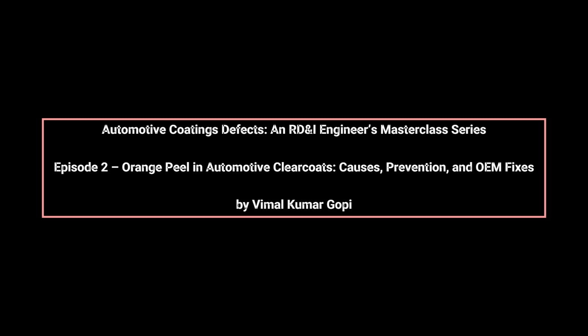OEM plants often use temperature-controlled pre-flash booths or slow reducers during hot weather to extend the open time and allow the wet film to flatten fully. Film thickness, or DFT, is another primary contributor. A thin film may lack the volume to create sufficient surface flow, while a thick film increases solvent retention beneath a quickly skinning top layer, enhancing the risk of orange peel.